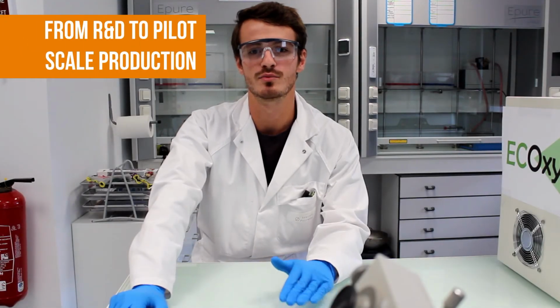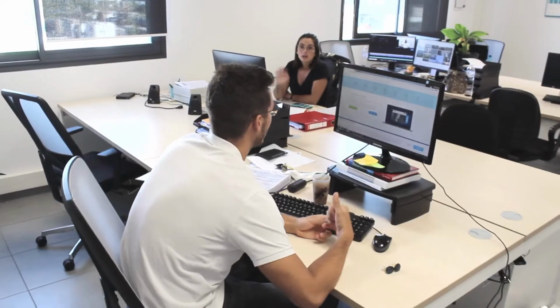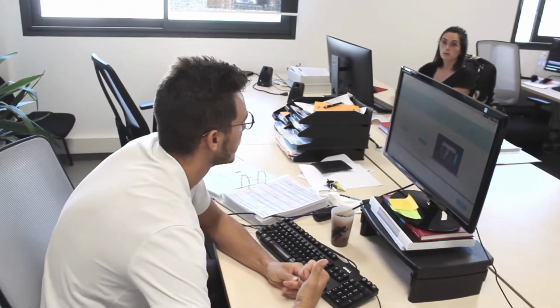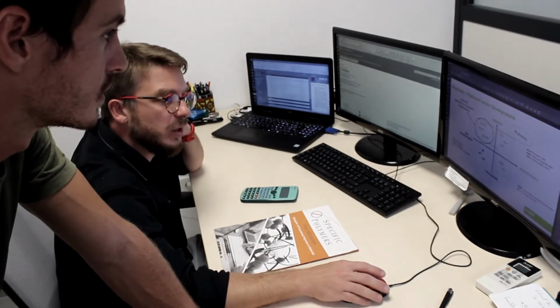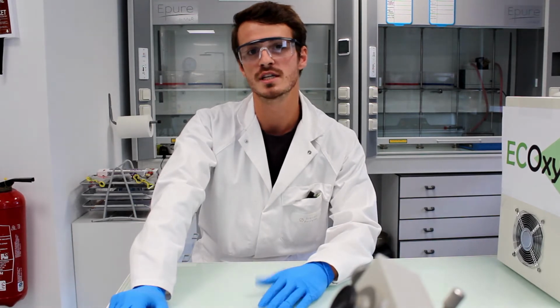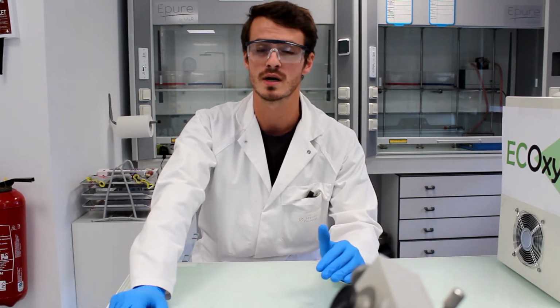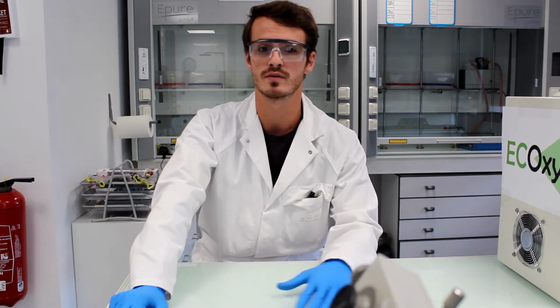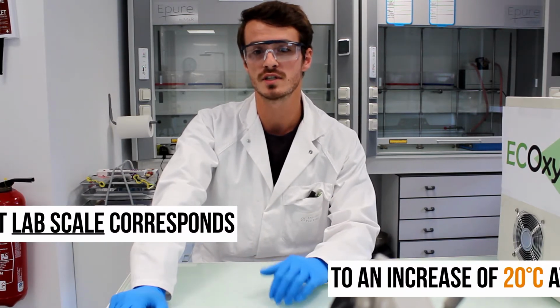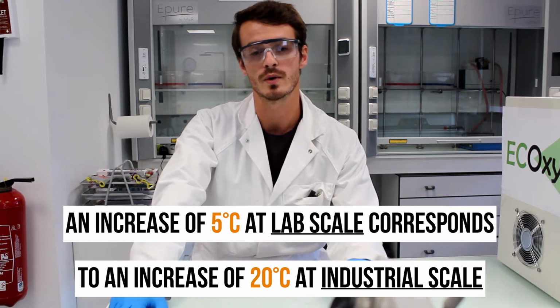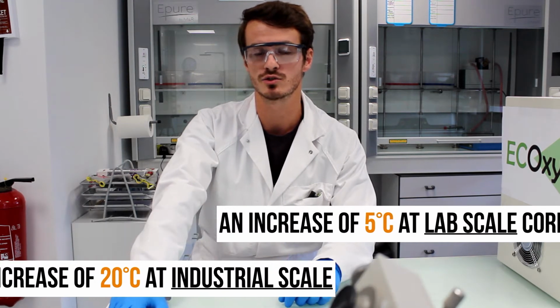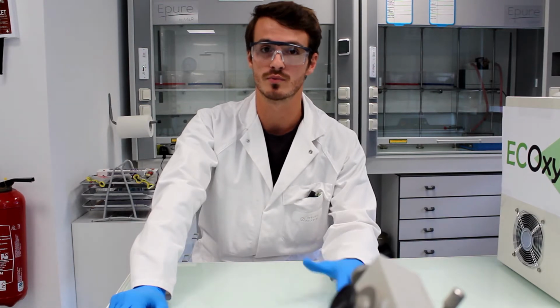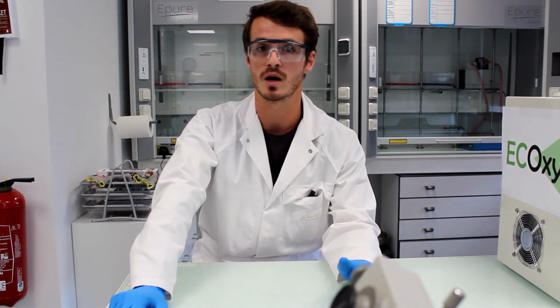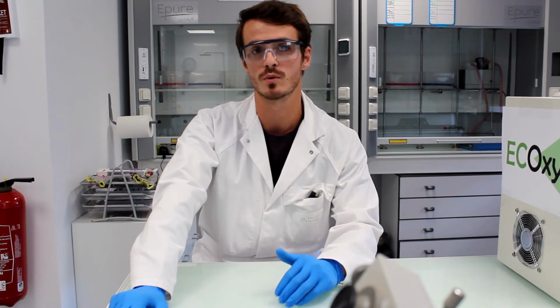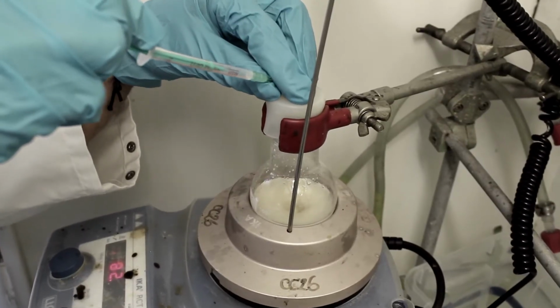Upscaling can be complex, it brings a lot of challenges to resolve before going further. In order to scale up any process, we have to strengthen all the experimental conditions we settle at lab scale and be sure that potential risks have been put aside. For instance, one key optimization is to master the exothermicity of the reaction to prevent safety issues. An increase of 5 degrees of the reaction media at lab scale corresponds to an increase of 20 degrees at industrial scale. It is more than important to find appropriate process routes to prevent thermal runaway and to make the overall process more robust. Thus we start at 5-10 gram scale.